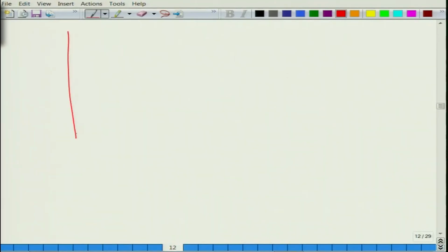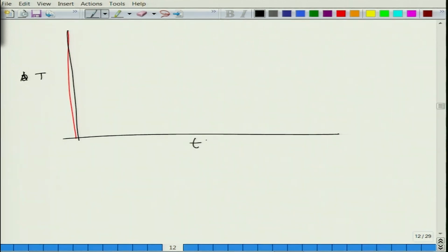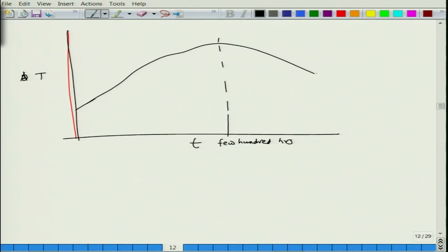So, that is why this process is a temperature dependent process. So, when you do age hardening of aluminum alloy, this is temperature versus time. You do it at such a temperature so that this is achieved after a very long time, let us say a few hundred hours. So, about 150-200 degree centigrade, and this is where your theta double prime to theta prime transition occurs.